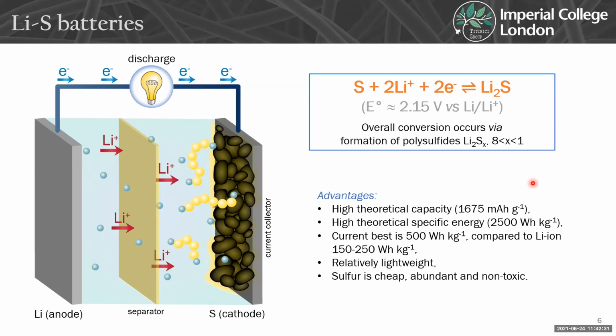The advantage of this system is that sulfur has a really high theoretical capacity, and that means overall we can have quite a high theoretical specific energy in the cell. Obviously this is a huge number that is probably not achievable, but the current best at the moment is about 500 watt hours per kilogram, and that compares to the lithium ion maximum of really 250. I think Tesla recently claimed 300 watt hours per kilogram. It's relatively lightweight, and sulfur is cheap, abundant and non-toxic, and it's actually a byproduct of the petroleum refining industry.